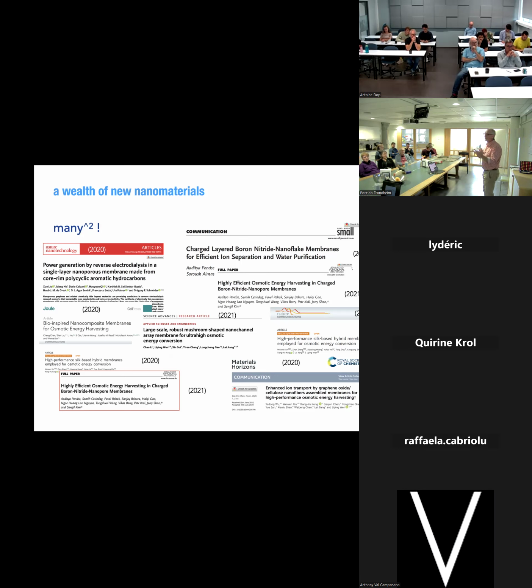Because we were looking at single nanotubes, but these membranes were also very highly efficient, in agreement with what we found for the single nanotube. What I find interesting is that there is an excitation to find new materials. And so that's where you have a revival of this osmotic energy, because instead of going only to desalination membranes or standard cation and anion selective membranes, you explore many materials. And the fact that you have diffusio-osmosis instead of bare osmosis means that you can have pores which are extremely large. You don't need extremely small pores. So this opens completely the space for the screening.